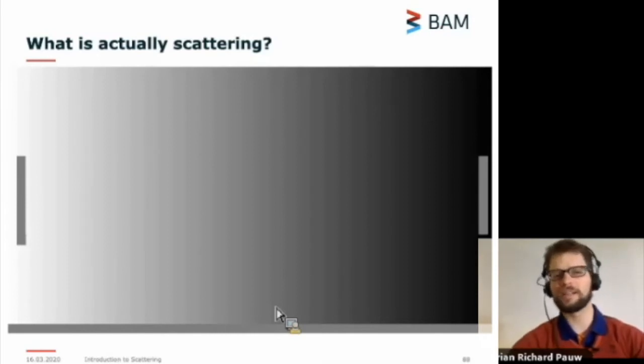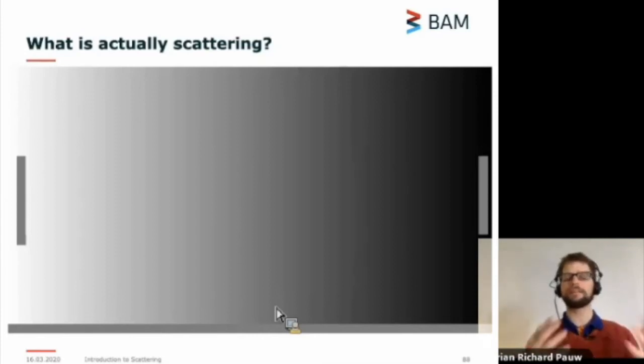So polystyrene has a density of 1.04 gravimetric, and water a density of 0.998. So this contrast is very, very, very small, and we have no chance of measuring this in our instrument. With biological samples, it's a little bit dependent on what you're actually measuring, but the contrasts there can be very low as well. So there you need a relatively high concentration of proteins, for example, or folded DNA fragments before you can actually detect a good enough signal over your background.